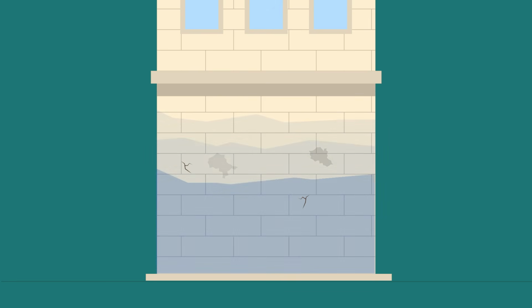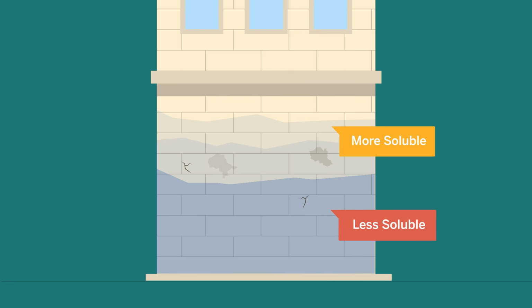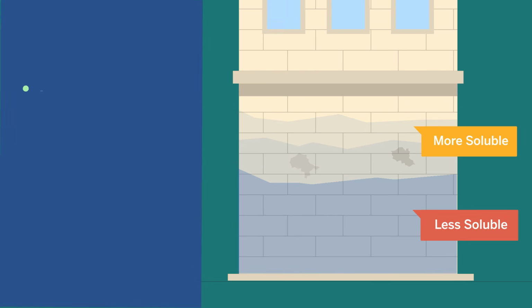As reported by Arnold and Zehnder, this can imply that zones showing damage may be found between two moist layers, whereby the upper moist zone would contain the more soluble salts. This separation must, however, be evaluated from case to case, as it will depend on the salt mixture, the substrate properties, and the exposure conditions.